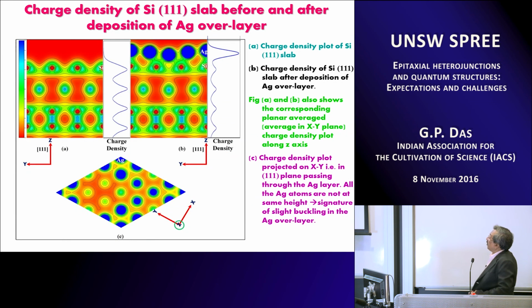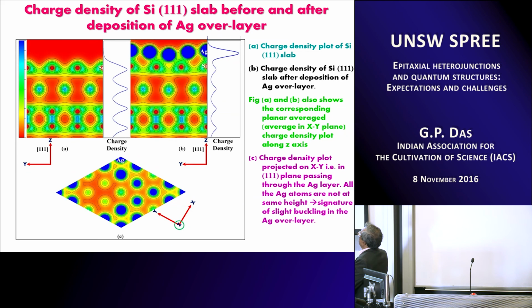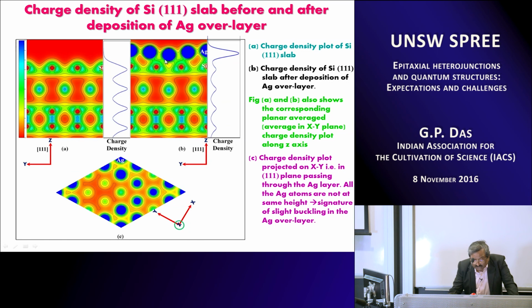Here are the charge density contours, which is very interesting because you can do it only by doing a DFT calculation, and it is clear that, look at this, 5 surface atoms of silver on 4 surface atoms of silicon, 1, 2, 3, 4. So the nature of bonding between silver and silicon is shown very clearly by this self-consistent charge density contour. Whereas when you go further down, that is on the silicon side of the interface, you can clearly see the covalent bonding in the silicon 111. So the charge density contour clearly establishes the kind of asymmetry in the surface charge densities, and you can see that the right half of the charge density and the left half have an asymmetry.